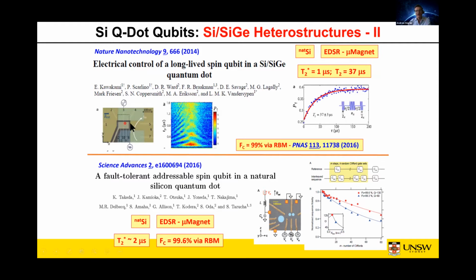An alternative approach is to use an on-chip micromagnet. So by fabricating a micromagnet on the surface of a quantum dot device, one can create an artificial, effectively spin orbit coupling, so that when one moves an electron within a magnetic field gradient, one can electrically move the electron around, simply applying a microwave signal to a gate electrode, to move this electron in the static magnetic field, and that creates an effective spin resonance. This is called either electric dipole spin resonance or electrically driven spin resonance. And so Lieven Vandersypen's group in Delft and Seigo Tarucha's group, originally at University of Tokyo, now at RIKEN, have really been the leaders of this technology. And also more recently, Jason Petta has been using this technology as well at Princeton. And those groups have all made great strides in both 1 and 2 qubit gates using electrically driven spin resonance in silicon germanium.